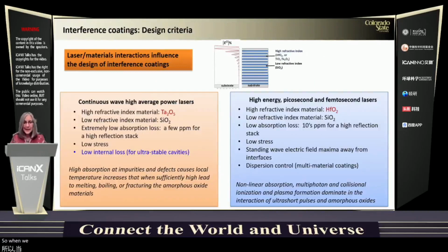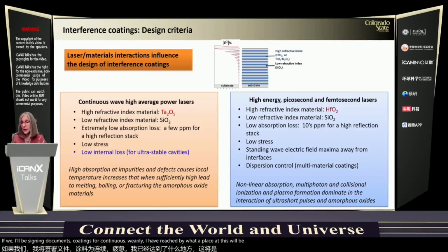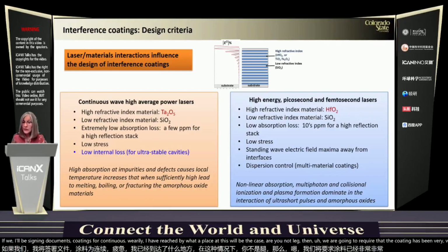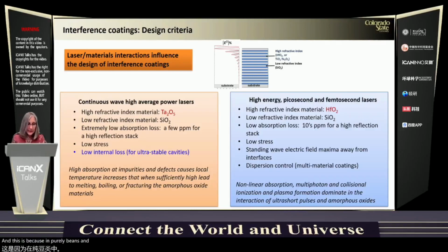So when we design interference coatings, there are many aspects that we need to look for. If we are designing interference coatings for continuous wave, high average power lasers, this will be the case of LIGO, then we are going to require that the coating has very, very low absorption of a few parts per million. And this is because impurities and defects cause local temperature increases that, when they reach a sufficiently high temperature, can lead to melting, boiling, fracturing of the amorphous layers.